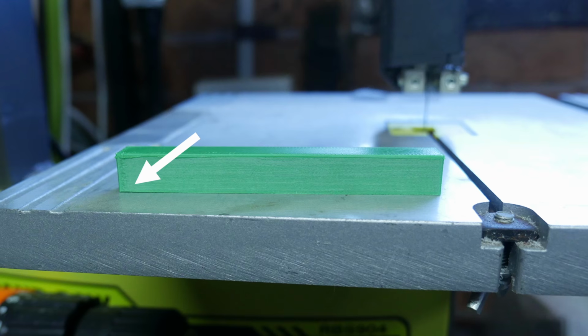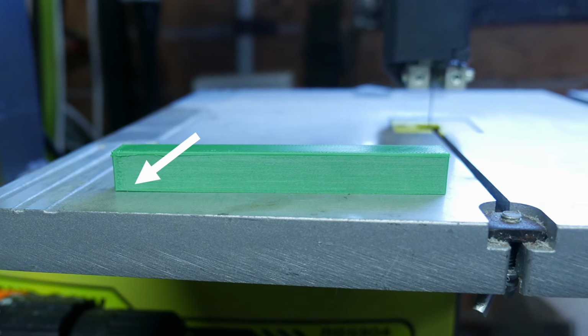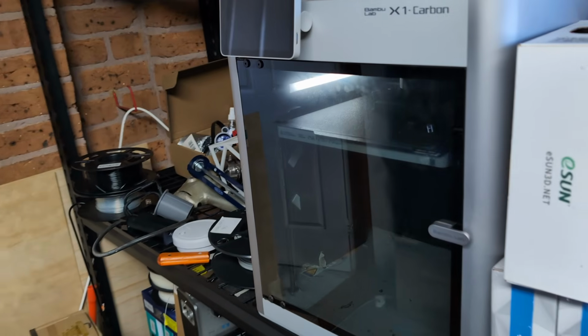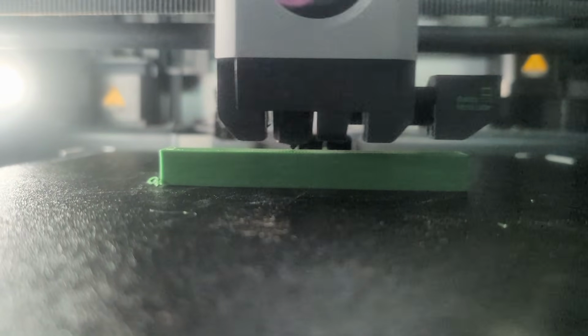But if you want to print ABS or filaments that warp, this is still not the right solution because the part will still warp, if not on the bed, then higher up. You need a chamber with high ambient temperature to print ABS with any degree of dimensional accuracy. So that's the real hack here. Keep the ambient temp high with an enclosure or use a printer that is enclosed. As long as your printing surface is clean and suitable for your filament, you'll have no problems at all with bed adhesion.